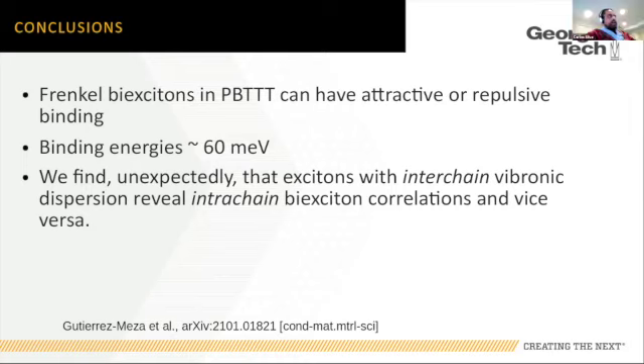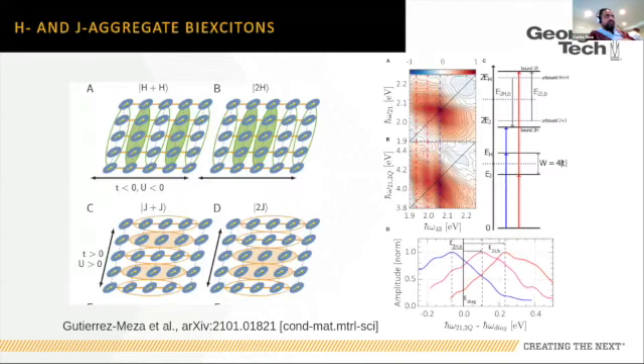So I didn't emphasize what I should have, because I was trying to rush through this. Every spectrum, and I only showed you 2, is at 0 population waiting time. Well, technically not 0, because at 0 time we have ambiguity in the time ordering of the pulses, but they're about a pulse width away, something like 20 femtoseconds. And so they're at very early time. There hasn't been enough time for any population relaxation, so this is essentially 0 time.